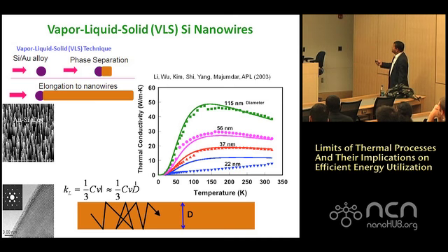This is thermal conductivity as a function of temperature for different sizes, 115 nanometers, 56, 37, 22. Even this is on the order of 50, whereas bulk silicon is 140. So you can say right away that the mean free path in the bulk is certainly larger than 115 nanometers, and in fact on the order of 300, 400 nanometers, some of them about a micron. As you get down to 22, the theory, this is Boltzmann transport, does not match up. Some very interesting physics comes out of that itself. Nevertheless, you can control it. But even in this, at room temperature, which is our interest, it is at about 5 watts per meter Kelvin. That's just not good enough.